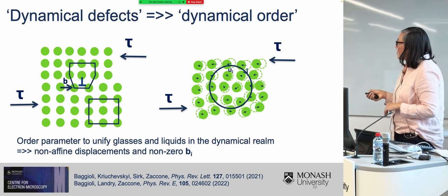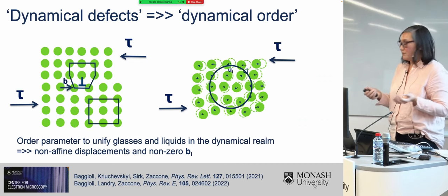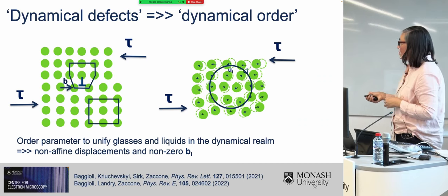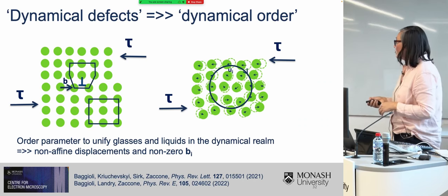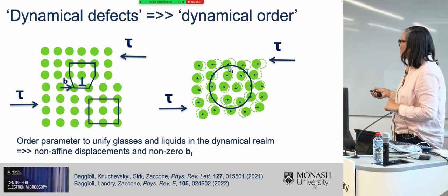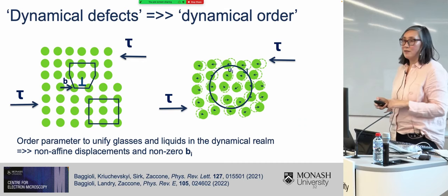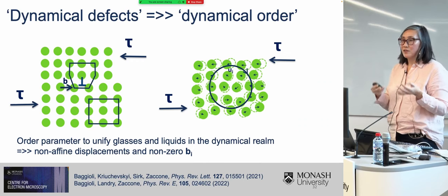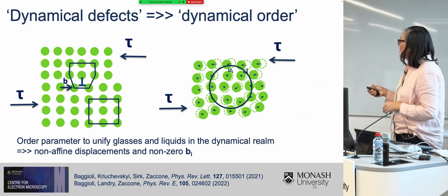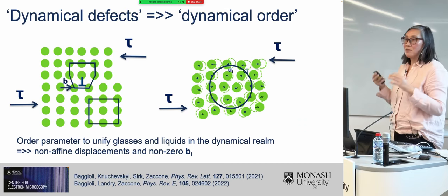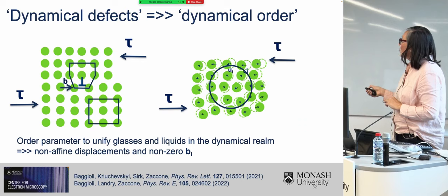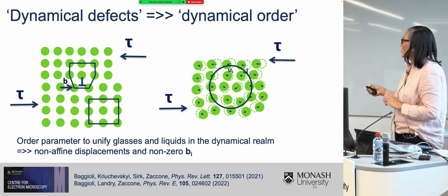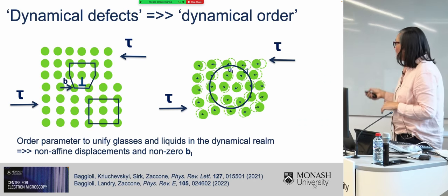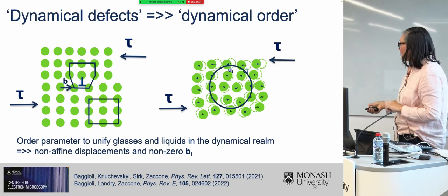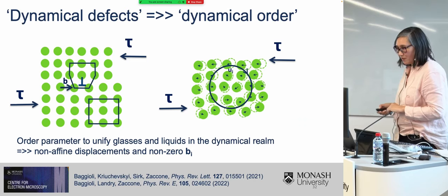Now, these are not defects that you can see in the static field, like crystals. So here you can measure a non-zero Burgers vector in the static structure of a crystal because the order parameter is very obvious. These are actually defects which you can only see in the displacement field or the dynamical field. And so what this suggests is that perhaps we should be looking for an order parameter in the dynamical field for glasses rather than in the static field. And if this is something that interests you, I suggest you have a look at these papers that have been written on the subject here.